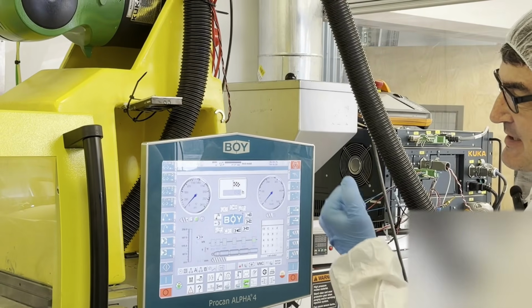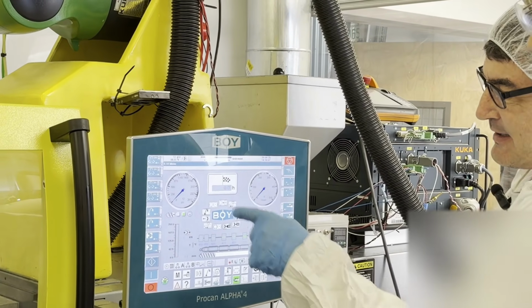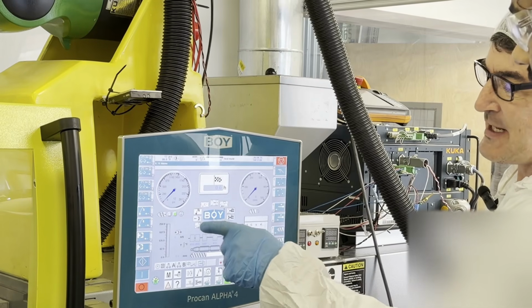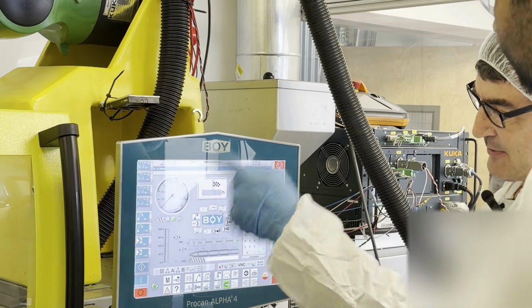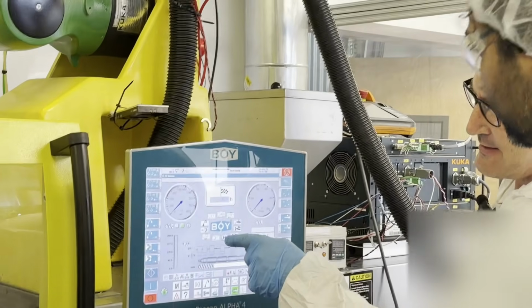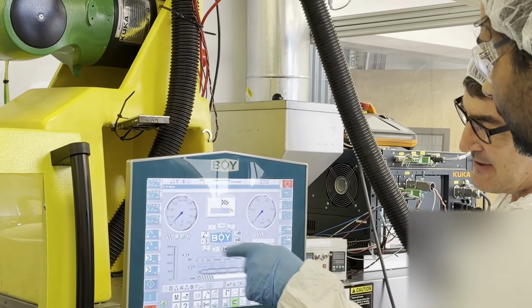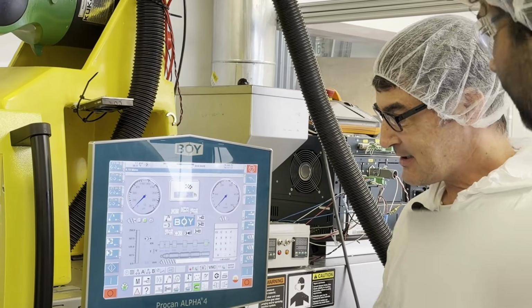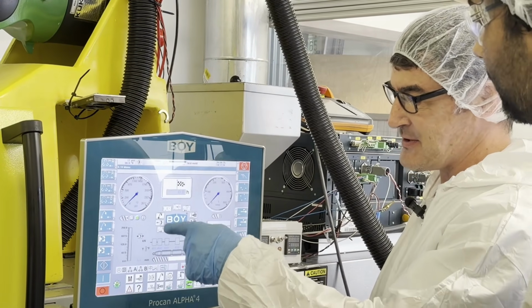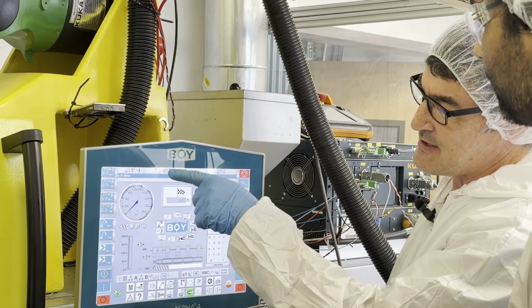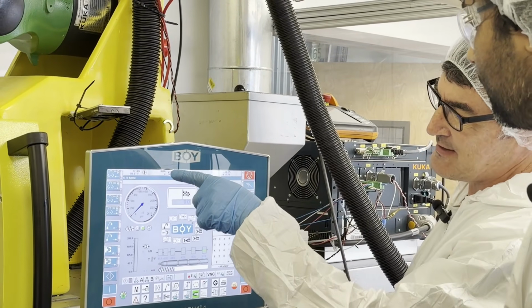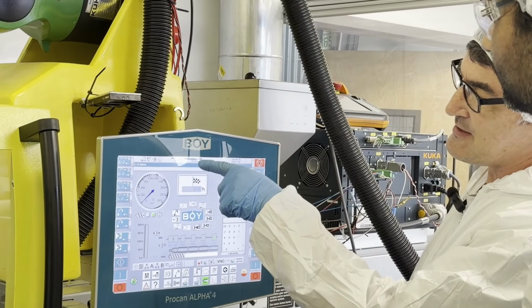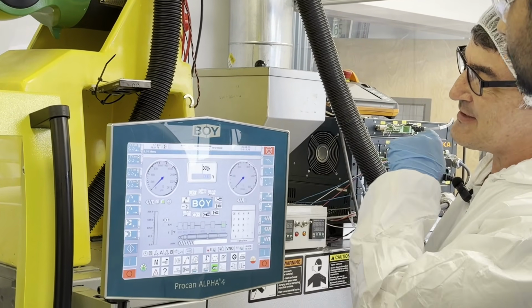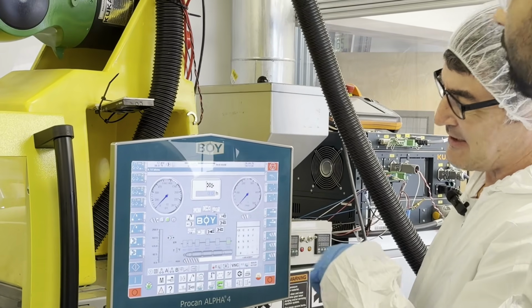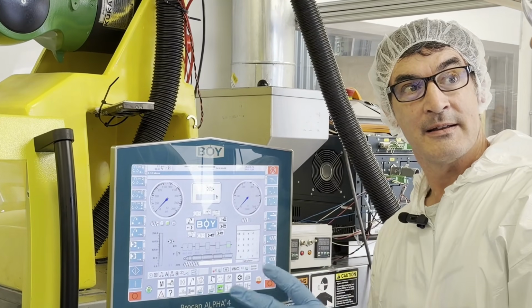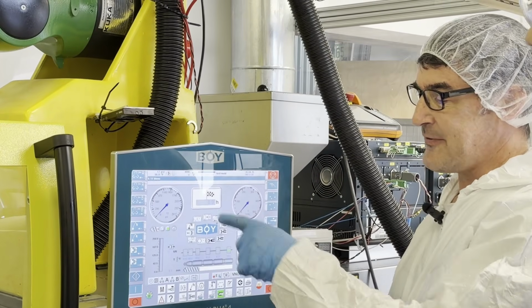Okay, so for this molding machine's operation, it provides this little track of major steps in injection molding on the screen, and as it's running through a part, it'll highlight each one of these, and it does this kind of continual circular, fully automatic molding operation. That's where you can just walk away, and it just goes through these steps until you reach the part count that you request, which in this case is 8,000 parts. Wow. And 21 seconds, or 21.27 seconds was the last cycle time for this particular part. So it can produce a part in 21.2 seconds. It can produce one part. Yes. That's amazing. A full cycle.